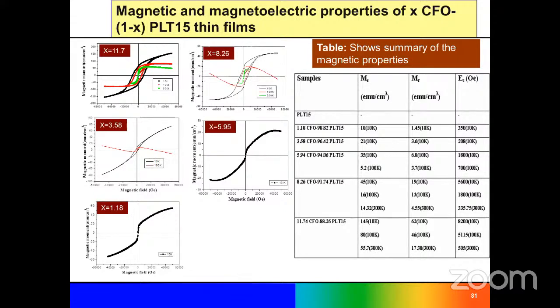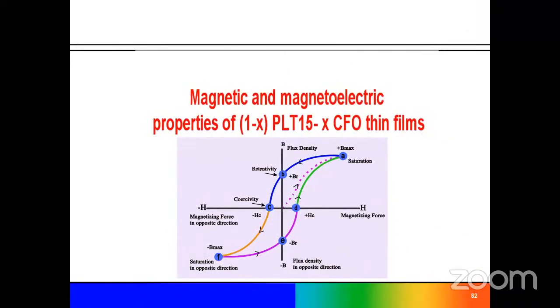And then we studied the magnetic properties of this material. We found that increasing the cobalt iron oxide in the PLT15 increases the magnetic property, also the saturation magnetization, and all other values increase with increasing cobalt iron oxide. So here, if you see the magnetoelectric properties in the PLT15, the different zones show different situations of the atom positions of these ferroelectric properties.